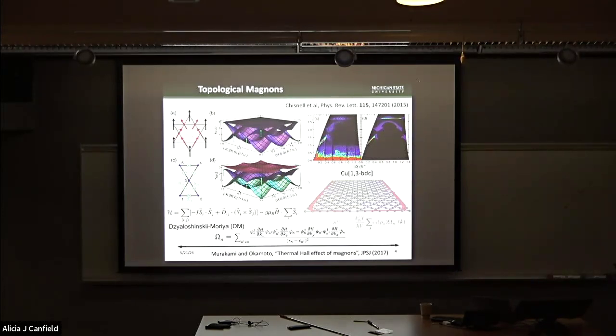And if we have a system that shows topological magnons, in the presence of a longitudinal thermal gradient, what do you expect to see? The thermal Hall effect. From this equation, we can immediately see that the thermal Hall signal is directly related to the Berry curvature of the gapped magnon band.